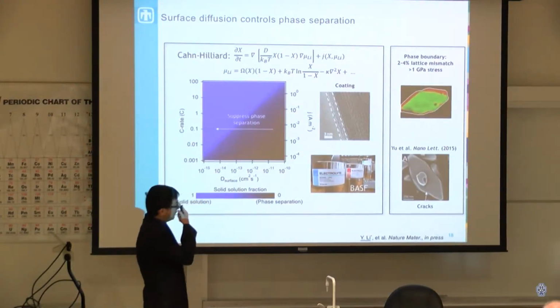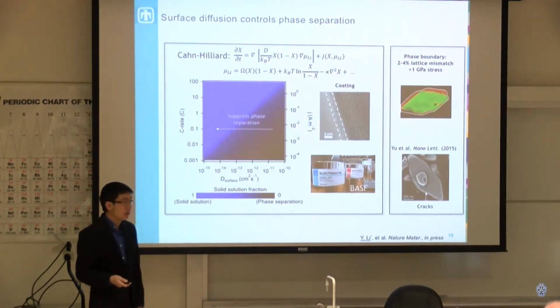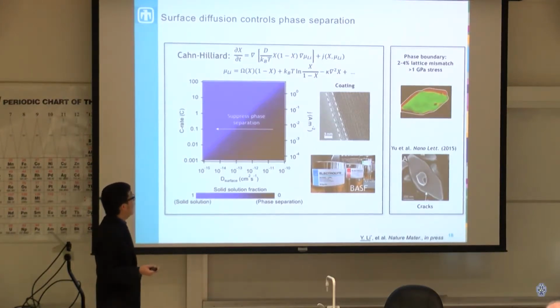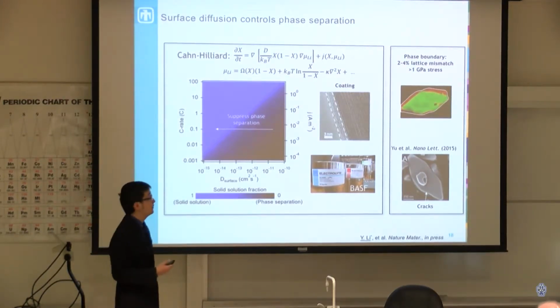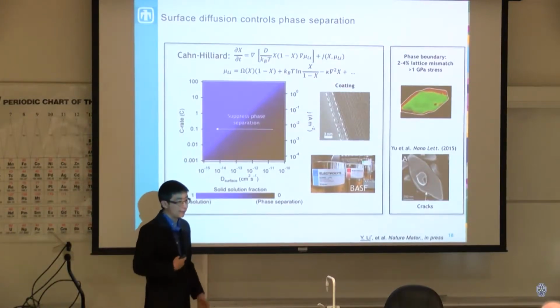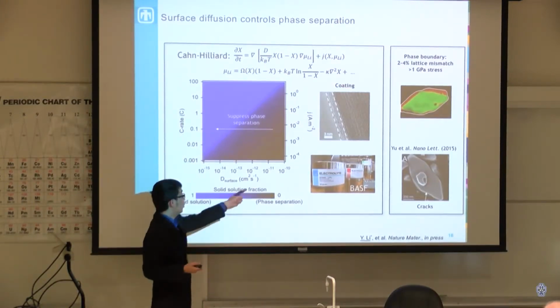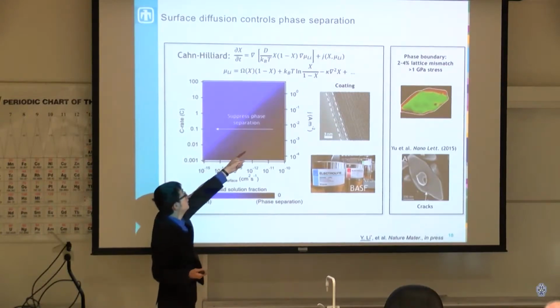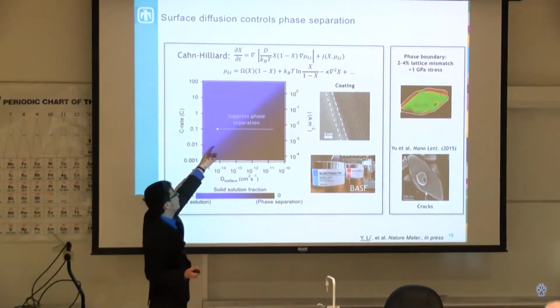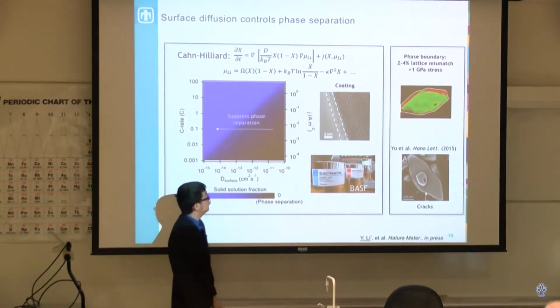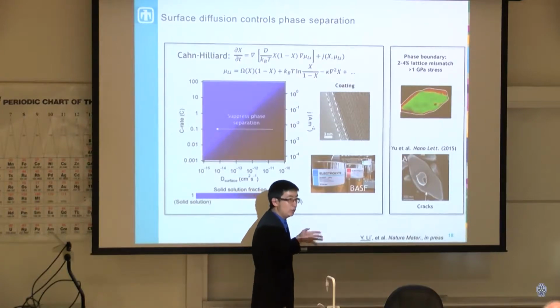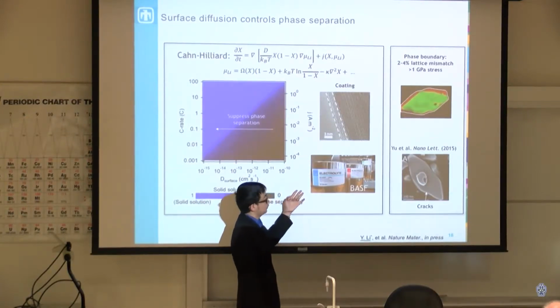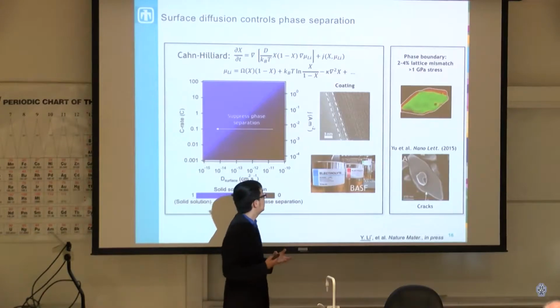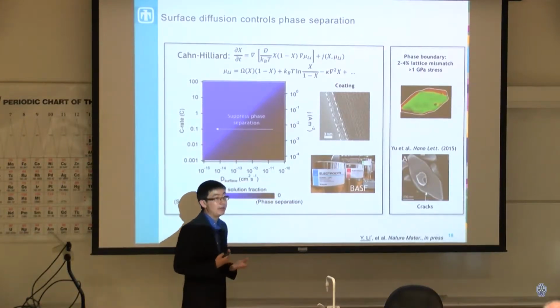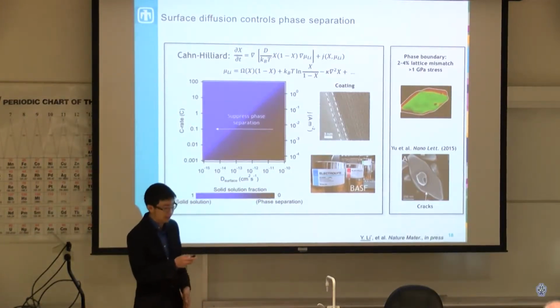Without going into too much detail, we did some reaction diffusion simulations to try to understand how this surface diffusion ultimately affects phase separation. What we find, consistent with intuition, is that the lower your surface diffusion, the more solid solution behavior you're going to have. So you can suppress phase separation by reducing the surface diffusion. What we are also trying to explore is using different surfaces and coatings to get these materials to not phase separate through this surface diffusional process.